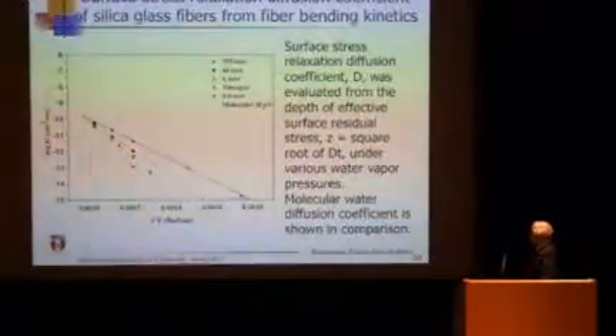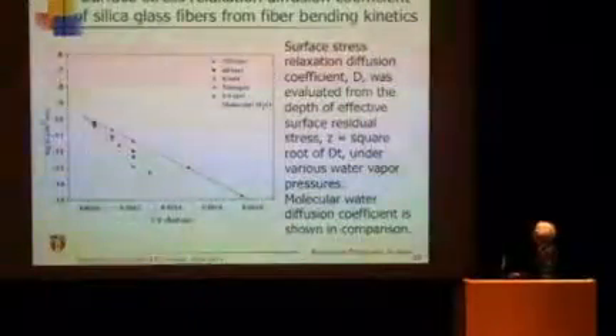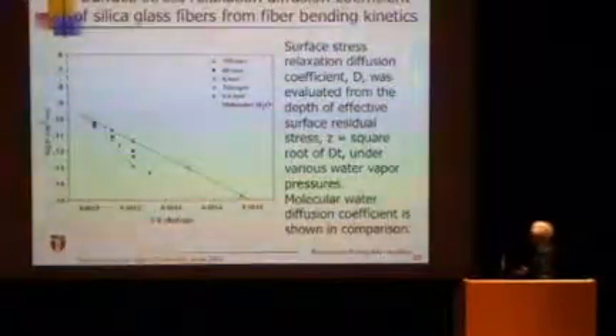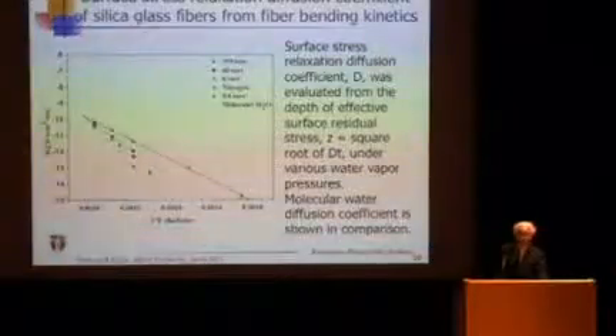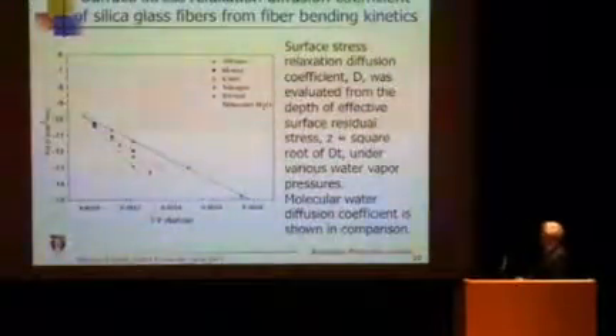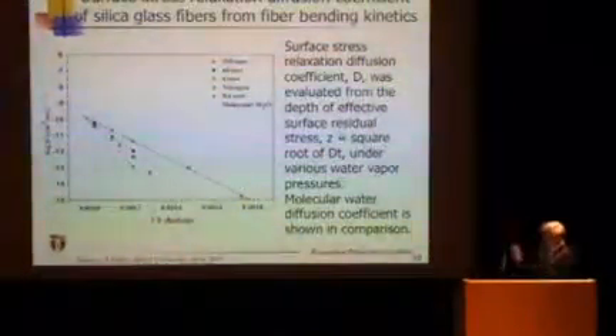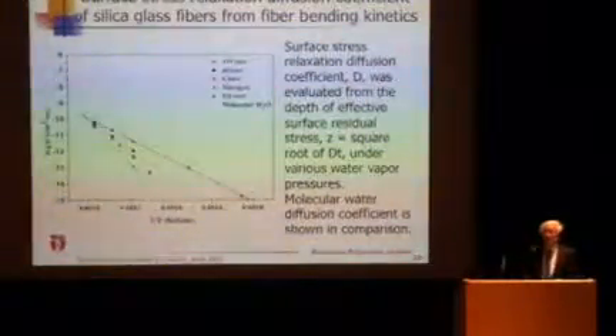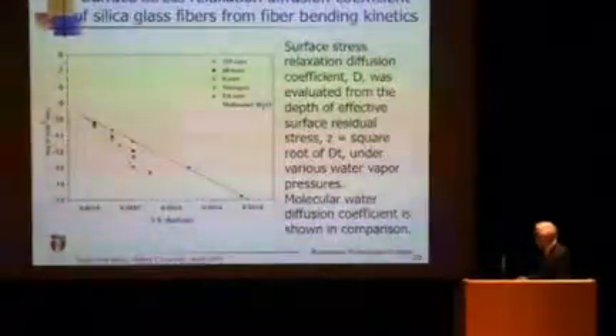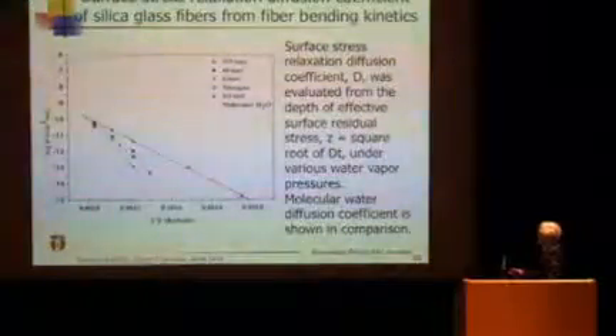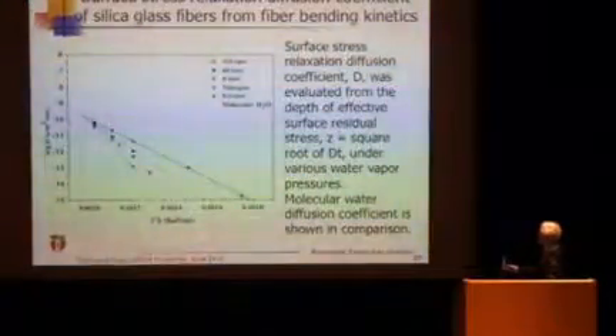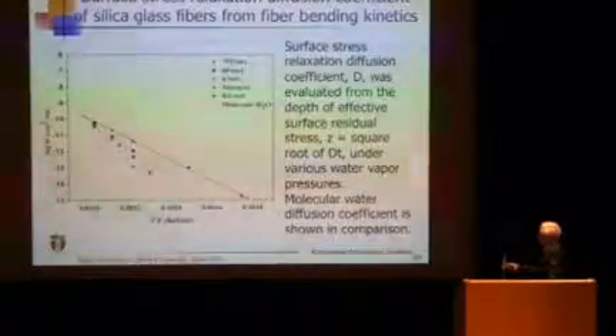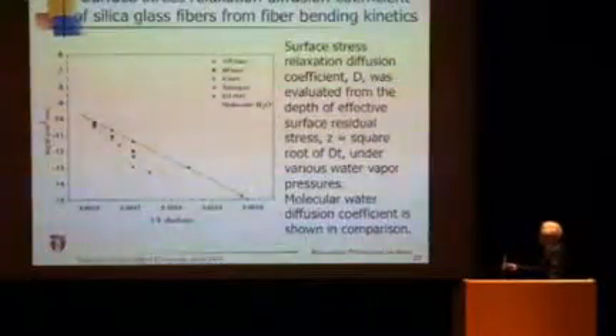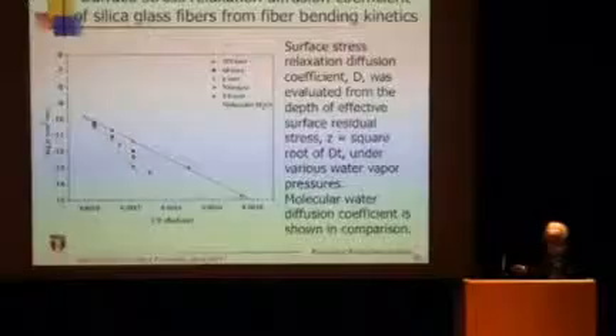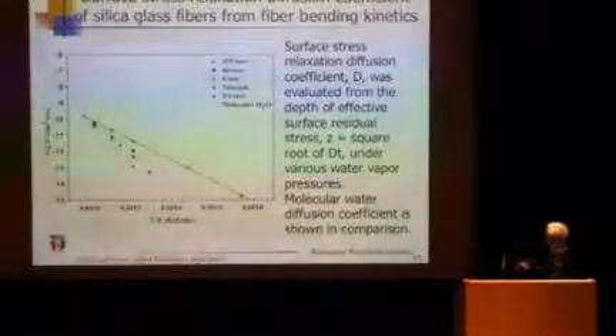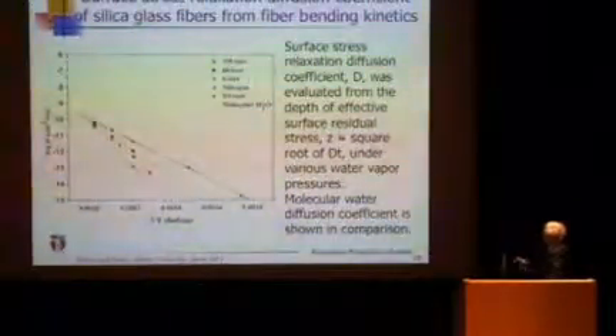So from this type of experiment, we got a diffusion constant called the surface stress relaxation diffusion constant. This is again an entirely new concept, that the surface is relaxing by a diffusion-controlled process. Of course, water diffusion is related. We found that as you change the water vapor pressure, higher water vapor pressure has a higher diffusion constant. And you can measure as low as 300 or 400 degrees centigrade for silica glass.